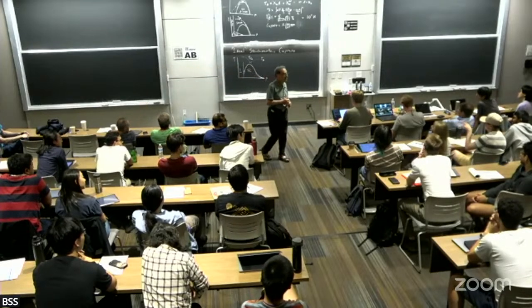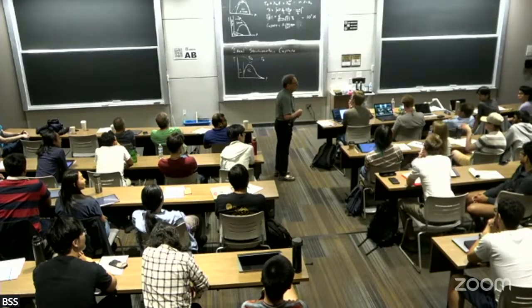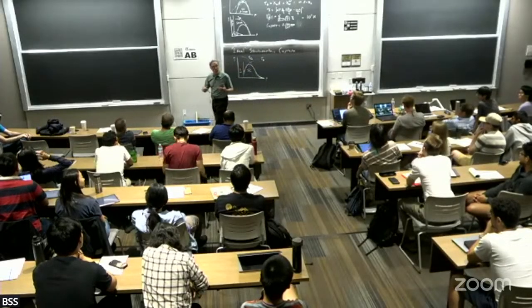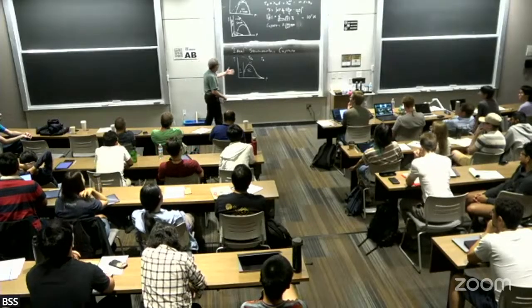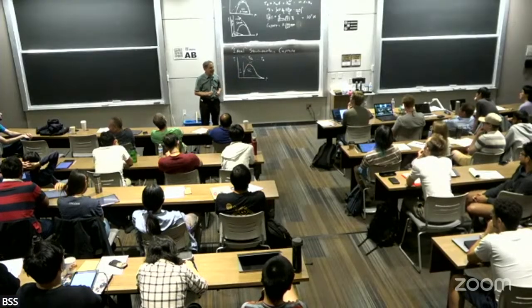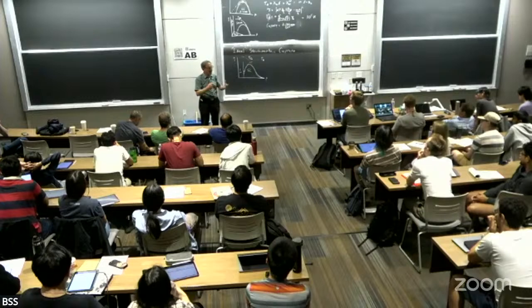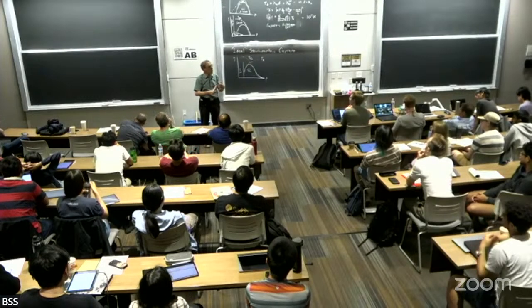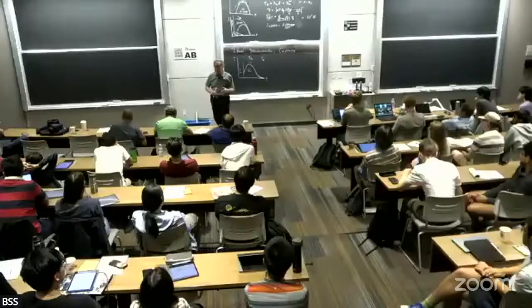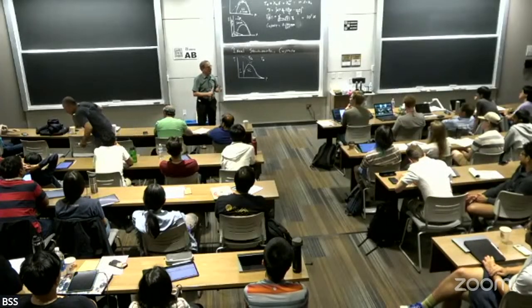Isn't the thing, like T delta and T theta are sort of competing? So there's certainly a broad theoretical reason for this. On the one hand, and we're wearing different hats when we say these things, but wearing one hat, we think that pairing is mediated by some sort of short-range antiferromagnetic fluctuations. And as you move farther away from the antiferromagnet, the degree of antiferromagnetic correlations is decreasing, and so the pairing scale is decreasing.